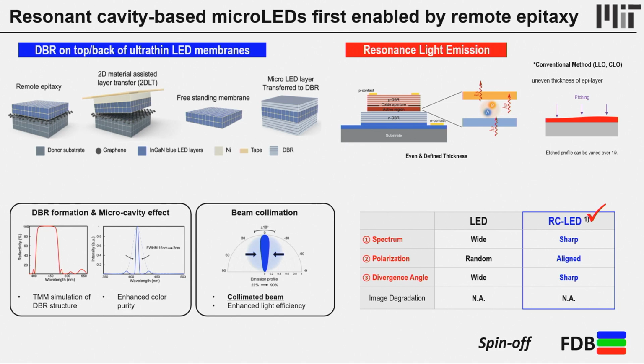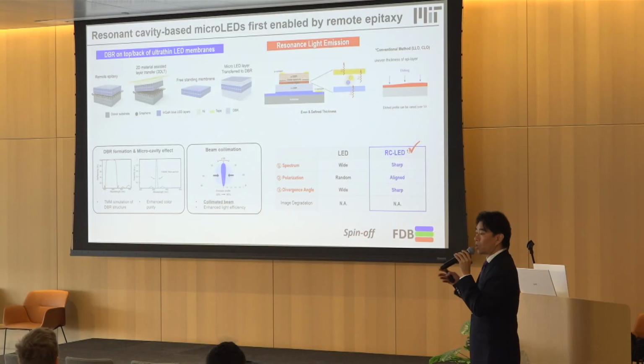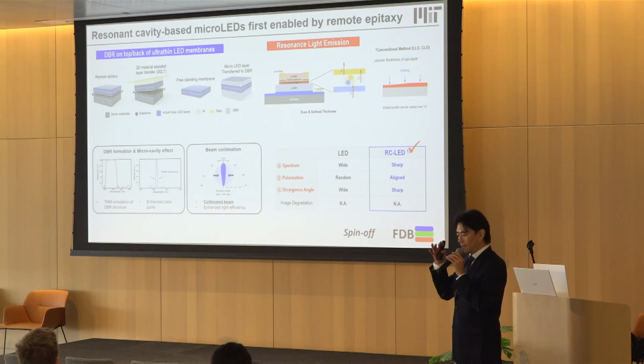Again, conventional techniques cannot do this because you have to grind or etch the membranes. Then it's irregular, and you cannot use precise optics there. But what we do here is DBR top and bottom. Then you can get a sharp spectrum, aligned polarization, and a sharp divergence angle. So then we can solve the substantial challenges in this field, the optics issues.